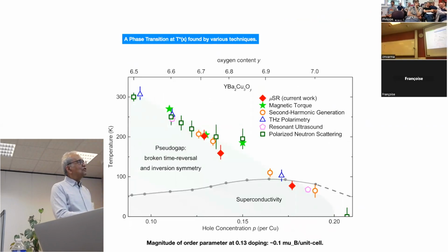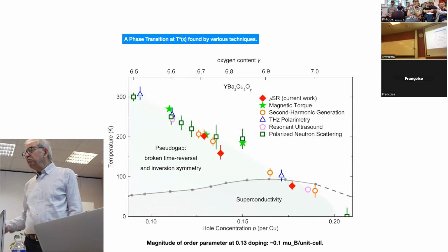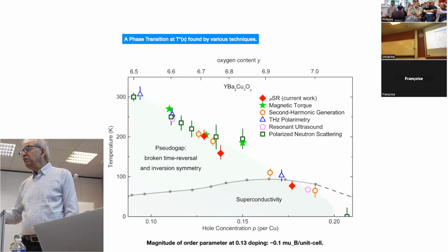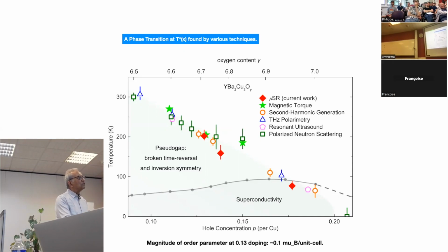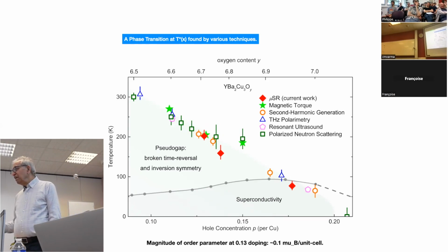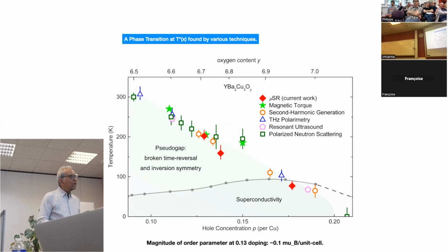And there are various other techniques used. For example, you can prove that if this magnetic pattern comes into being, the symmetry of the magnetic susceptibility in the unit cell will no longer be that of a square or a tetragon. Symmetry will change, and that can be measured by torque measurements, which was done here. And all these things kind of fell here, and there are some other techniques which are really not so specifically symmetry sensitive as the 4 techniques that I've described to you. And in the case of the cuprates, summing the 2 moments together, the maximum order parameter is about a tenth of a Bohr magneton per unit cell.